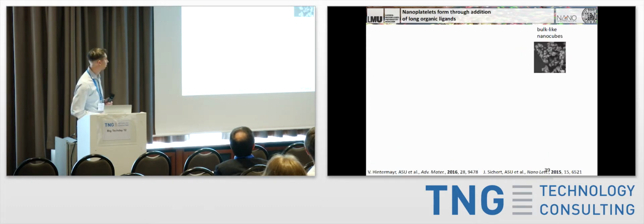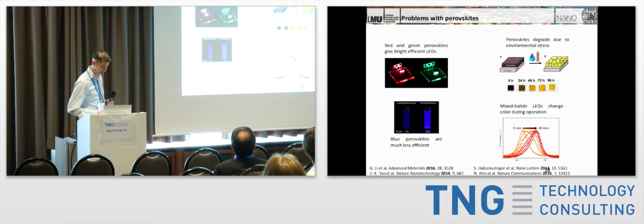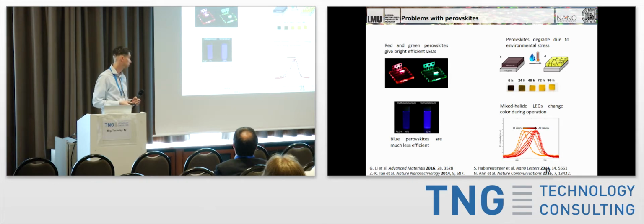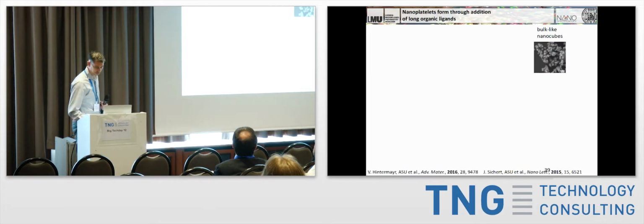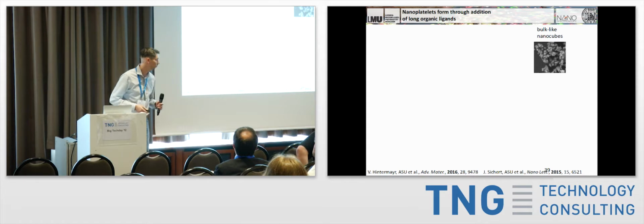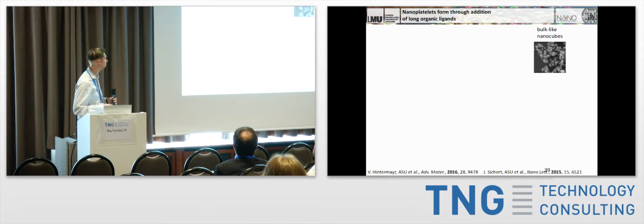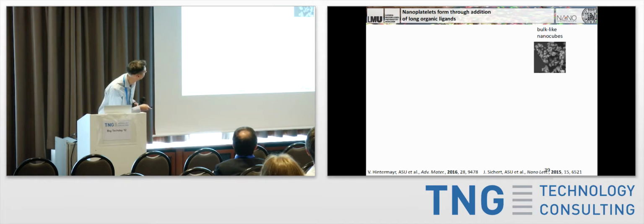All right, so some of the work that we've been doing is aimed to attack some of these strategies. So we've been mainly looking at overcoming some of these blue issues and also looking at stability of these nanocrystals. And so what we've been doing is, when the first nanocrystal was actually produced in 2014, we wanted to understand how the synthesis mechanism worked. And so essentially we copied one of the first papers that was out there, produced these nice bulk nanocubes. I think the scale bar is 200 nanometers in this case. You can see these nice cubes sitting in there.